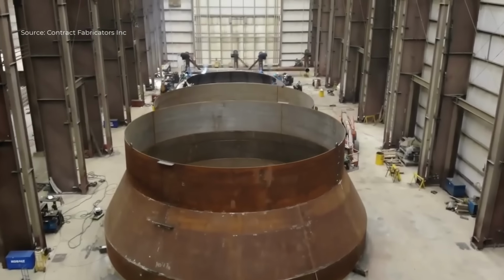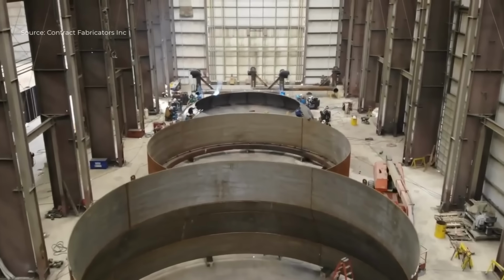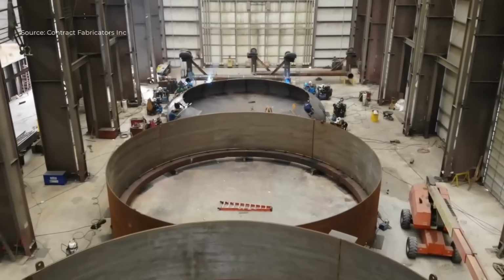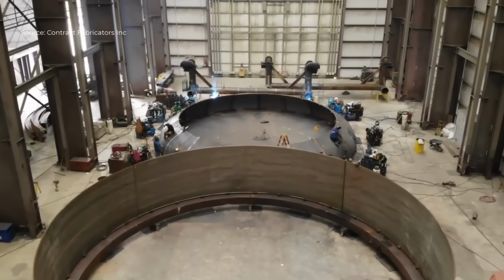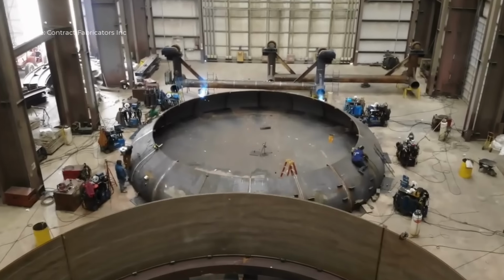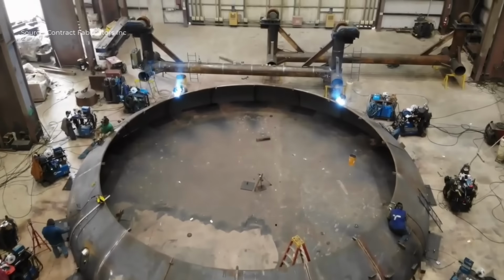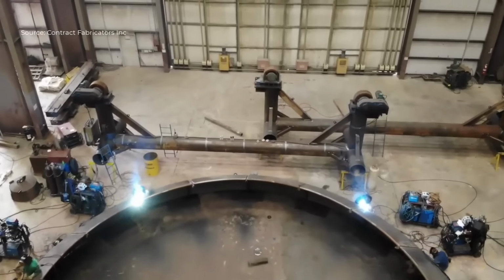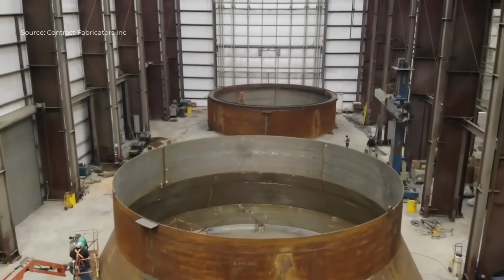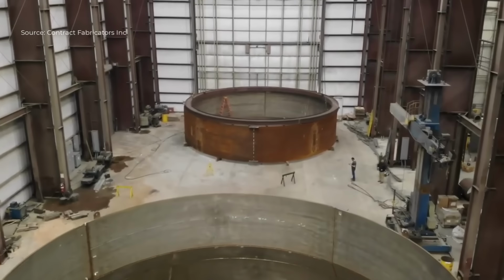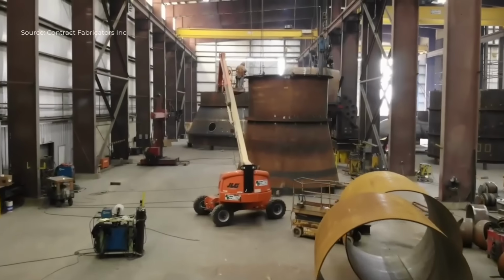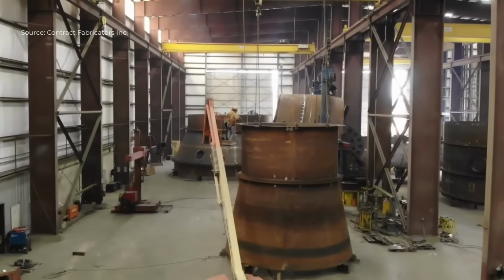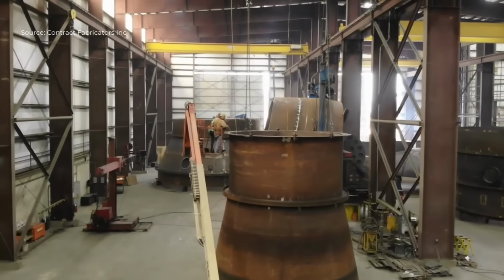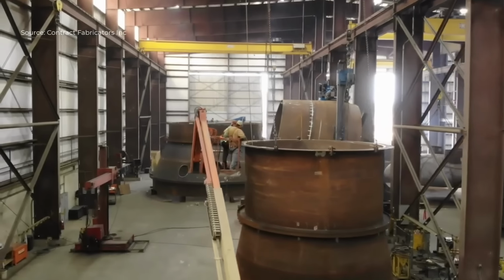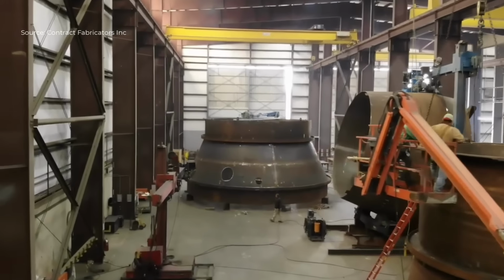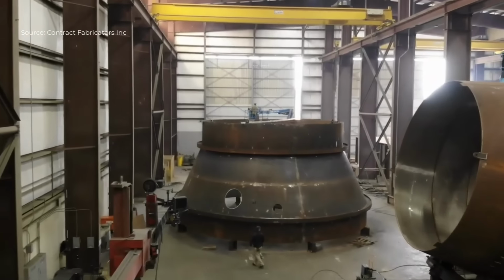The fabrication of an explosion-bonded clad pressure vessel begins with precise seam preparation. At each joint, the edges of the clad plate are carefully peeled back to expose the carbon steel backing material, ensuring access for welding. Next, the backing weld is performed, creating the primary pressure boundary that provides the vessel's structural integrity. Once the backing is fully joined, the clad restoration stage starts.